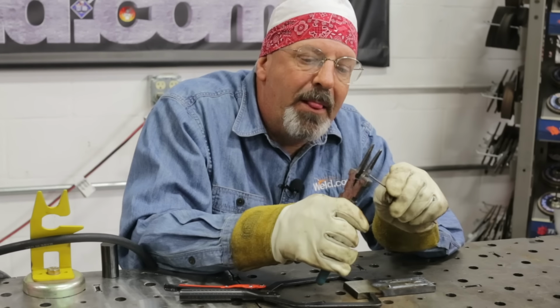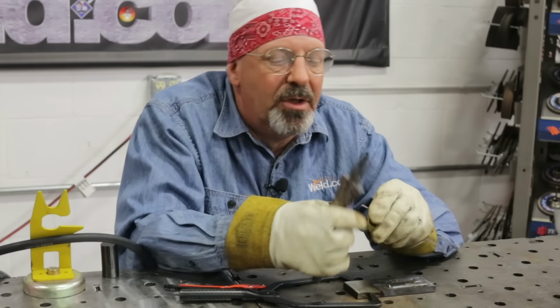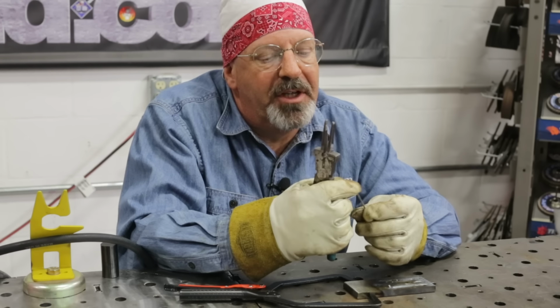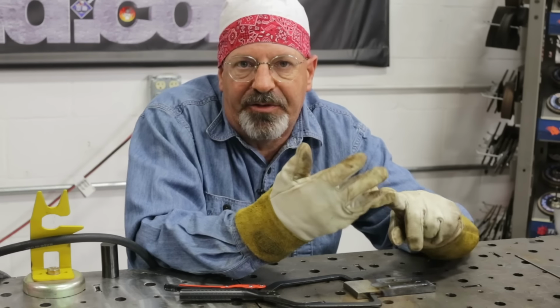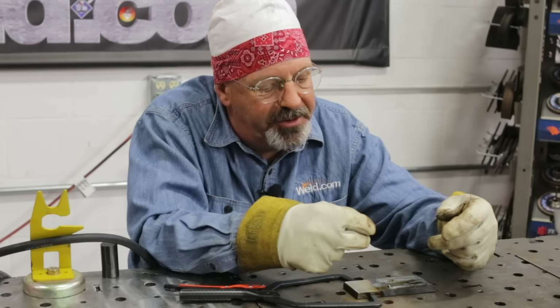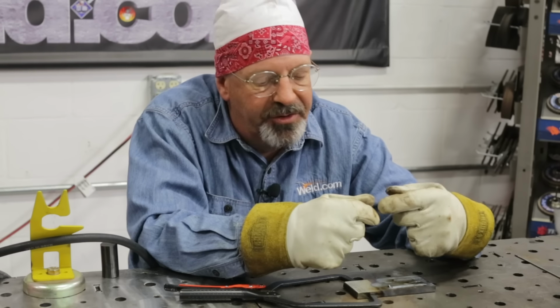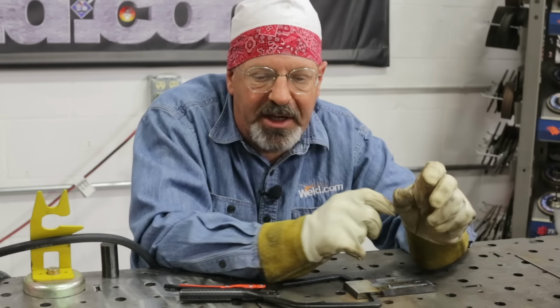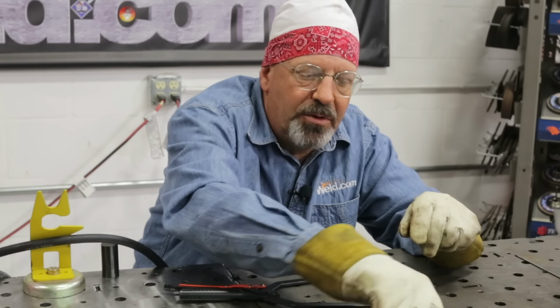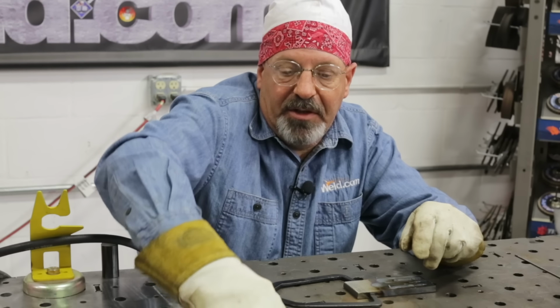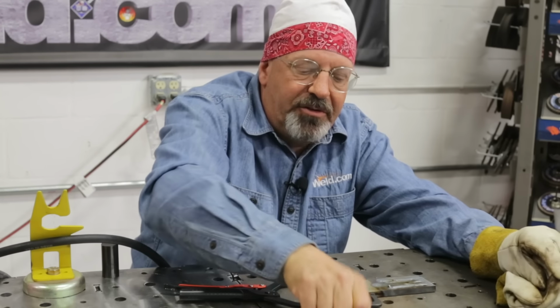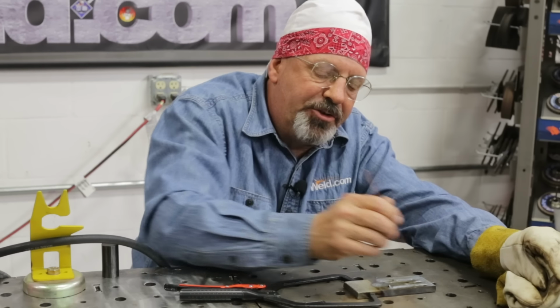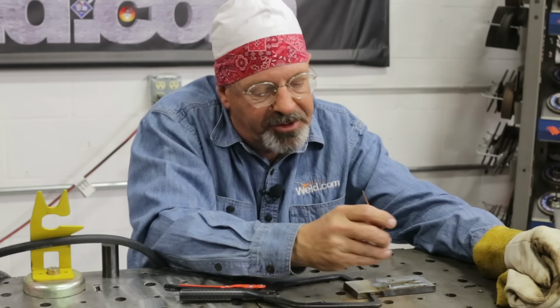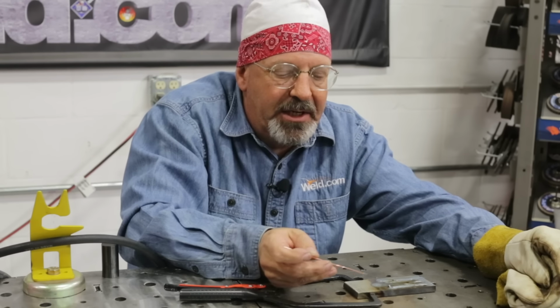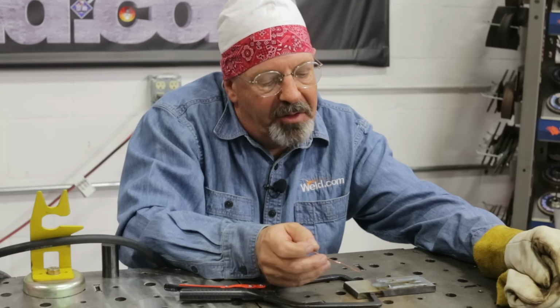So to close all this out, to dress this tungsten, snap that rascal off, take it over and regrind a tip on it and everything. To close all this out, we put a TIG torch together. We talked about angles, arc lengths, clear vision, being able to see, running straight lines. We ran beads with filler wire, too long of an arc length, too much angle. There's all these combinations. Just keep it real simple and follow the rules of 1/8 inch to start out with, 1/8 inch arc length, 10 to 15 degree lead angle in the direction that you're traveling. Get used to running multiple straight lines. Add your filler wire, bring it in low, 15-20 degrees. Put it on the leading edge of the pool.